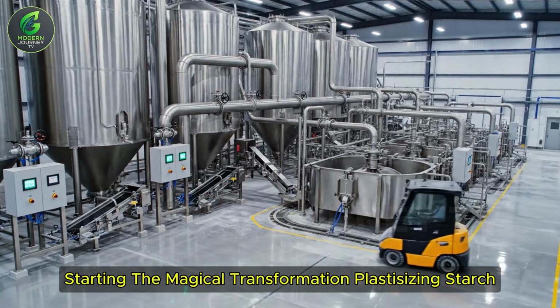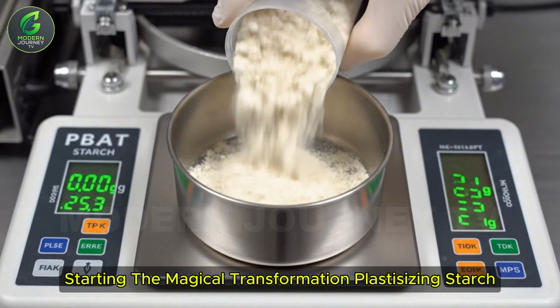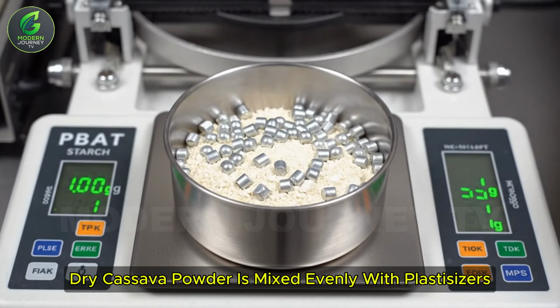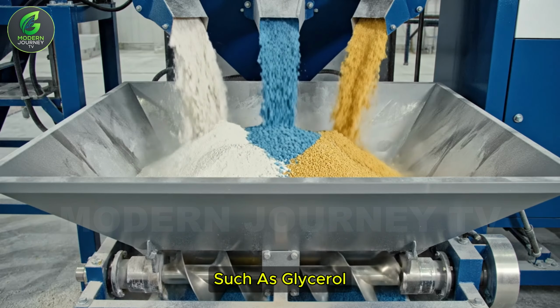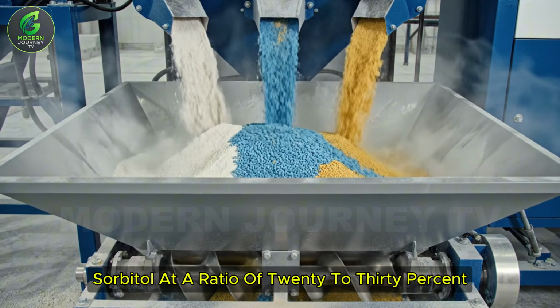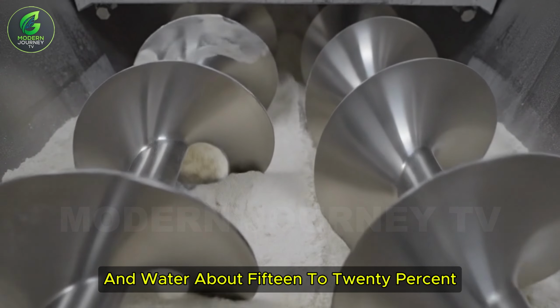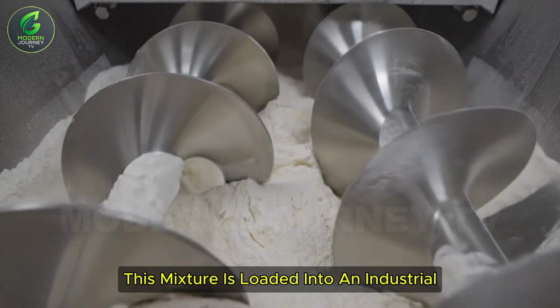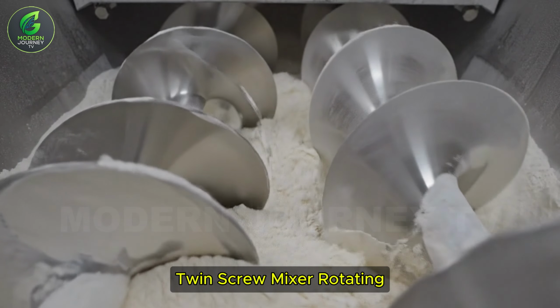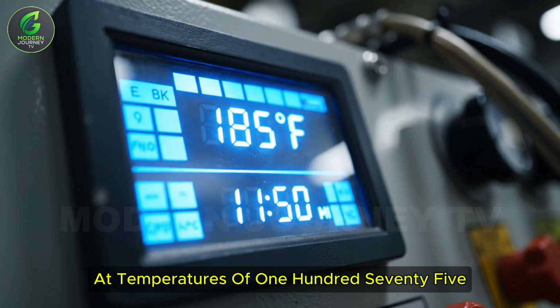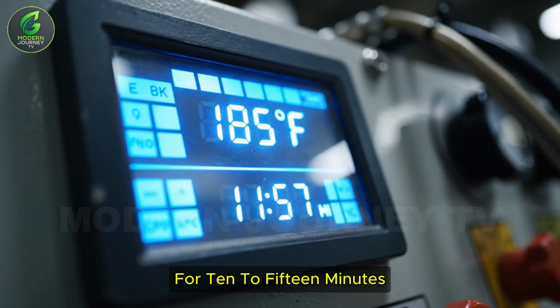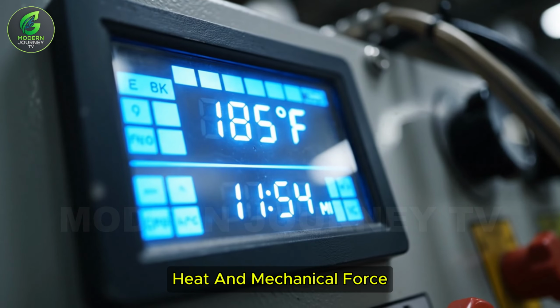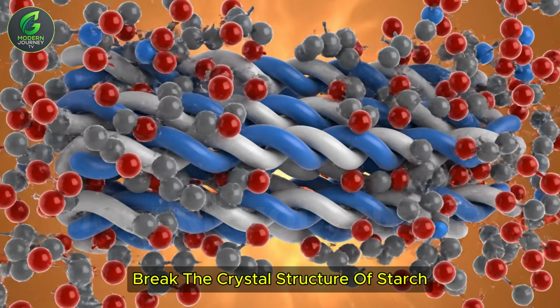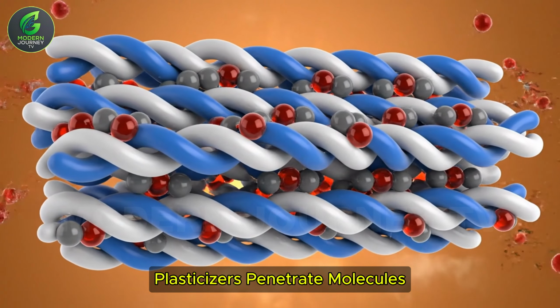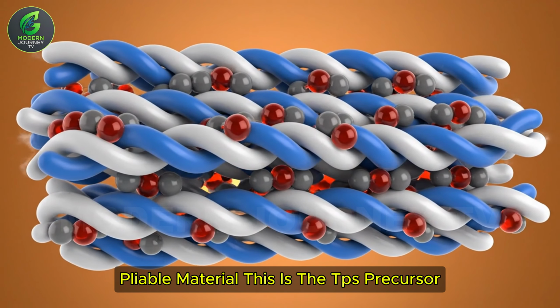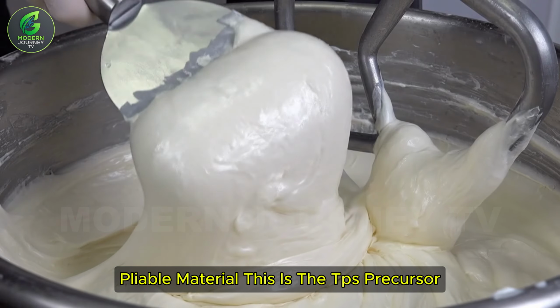Starting the magical transformation, plasticizing starch. Dry cassava powder is mixed evenly with plasticizers such as glycerol, sorbitol at a ratio of 20 to 30%, and water about 15 to 20%. This mixture is loaded into an industrial twin-screw mixer, rotating at temperatures of 175 to 200 degrees Fahrenheit for 10 to 15 minutes. Heat and mechanical force break the crystal structure of starch. Plasticizers penetrate molecules, turning hard starch into soft, pliable material. This is the TPS precursor.